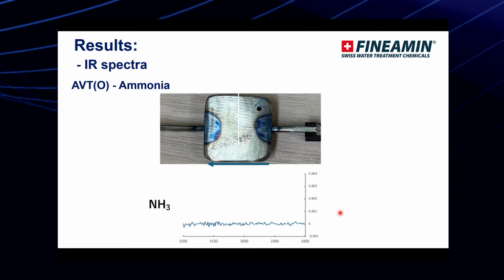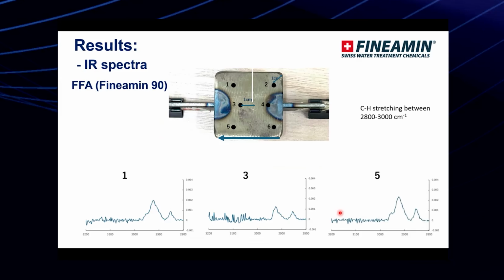It takes a little bit of time, but as you can see here, between the IR spectra, there is clear evidence of absorption on the metal plates in the dry steam, and we could see the absorption taking place based on the C-H bonding, carbon and hydrogen bonding. This is quite encouraging, I think, and we will continue to try to make the analysis. Research is an ongoing process.